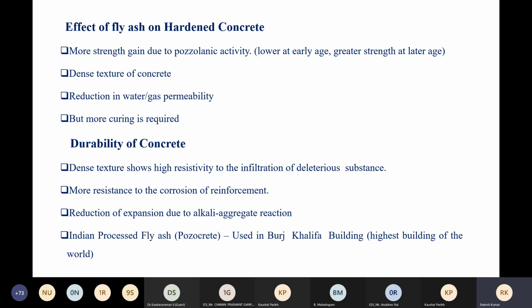Reduction in water and gas permeability. If there is less void, in that case permeability, either water or gas, will be reduced. So if the permeability is less, the foreign elements such as sulfate and chloride will not be introduced into the body of concrete, and it will make durable concrete. But more curing is required, because a continuous hydration process is required. When one side calcium hydroxide is liberated, that will start to react with the pozzolanic material. So curing is more required in this case.